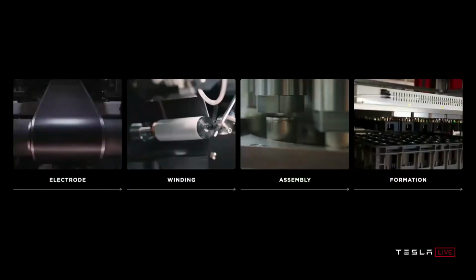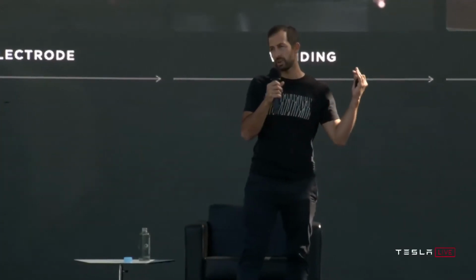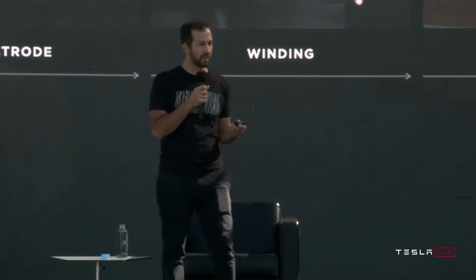Let's talk a little bit about what's in a cell factory. First, there's an electrode process where the active materials are coated into films onto foils. Then those coated foils are wound in the winding process we just talked about, where if you do have tabs, you have to start and stop a lot. Then the jelly roll is assembled into the can, sealed, filled with electrolyte, and then sent to formation, where the cell is charged for the first time, and where the electrochemistry is set and the quality of the cell is verified. And we set out at every step of this process to take that inspiration we just showed and think about how we make those processes fundamentally better and more scalable.